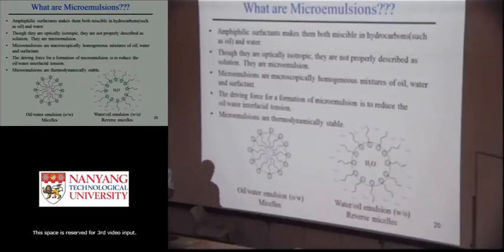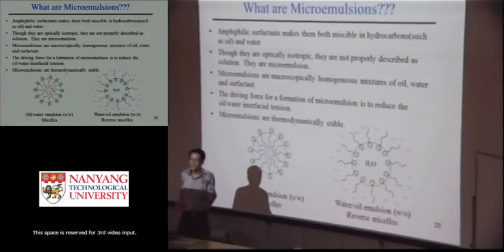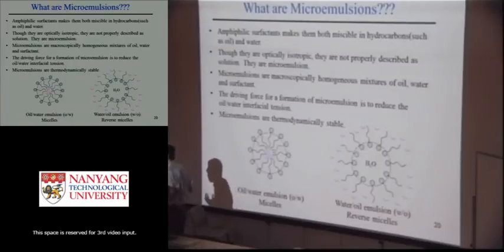The main reason is related to the selection of chemicals. It is very easy to choose some chemical that is only soluble in water but not soluble in oil. That is the case for, let's say, some inorganic nanocrystal synthesis. Let's say I want to make copper oxide. I choose some copper precursor, a copper chemical. I can choose a copper chemical that is only soluble in water but not soluble in oil. Copper chloride, copper sulfate, easy.